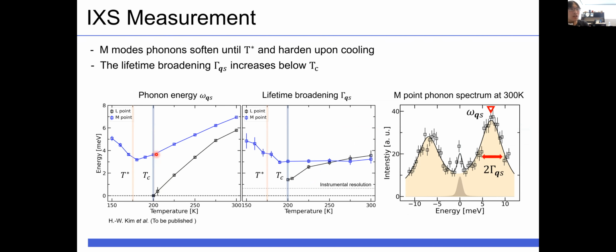The left figure is phonon energy and the right is the lifetime broadening, depending on the temperature. It means the width of the Lorentzian line shape. If we look at the phonon energies, you can check one more time that the M phonon does not condense at any temperature. It is soft until T star and hardens upon cooling.